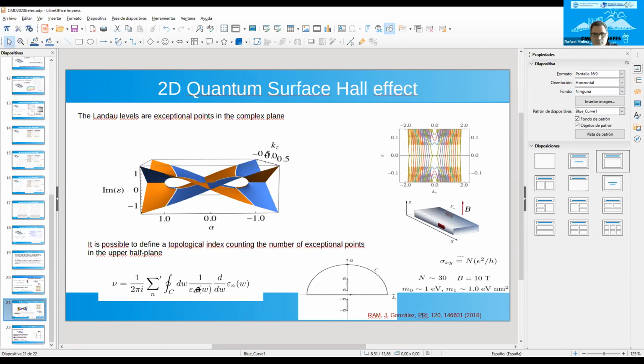Sorry, I was saying that working with Laszlo, we studied magnetotransport in nodal lines at the semi-classical level, and we found that it's extremely difficult to disentangle trivial and topological orbits. So I'm wondering how clean the signal of this Hall effect would be if, in these nice pictures, you have both trivial orbits and topological orbits.